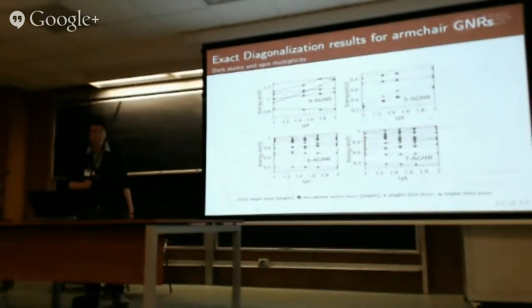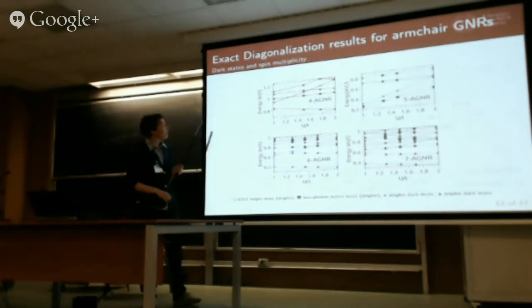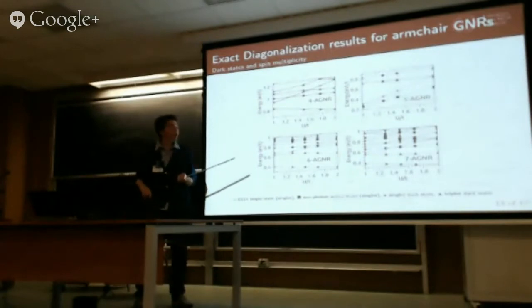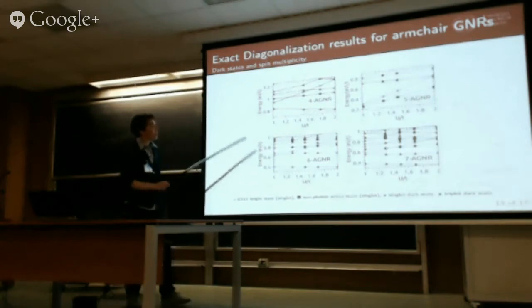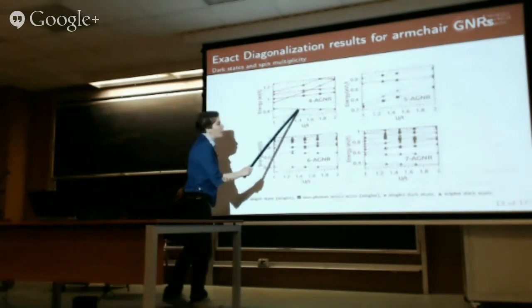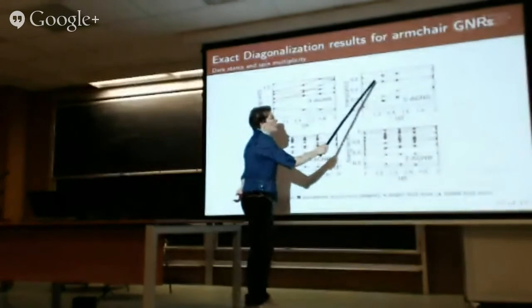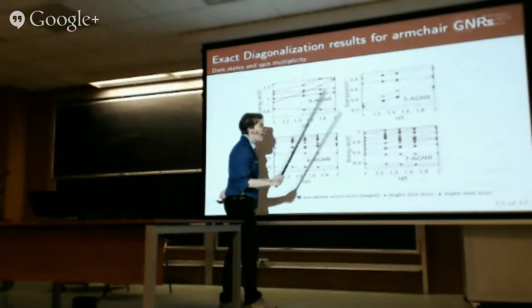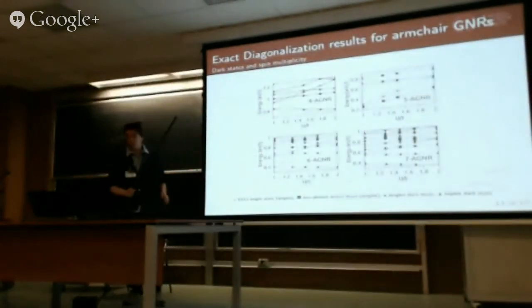I've also performed the spin multiplicity analysis of dark states, which are optically inactive excitonic states, which are believed to play an important role in quenching the photoluminescence quantum yield in these nanostructures. You can see that I found a few triplet states just above the ground state, and a few singlet dark states very close to the lowest bright one-photon singlet excitons. This was also found for carbon nanotubes.